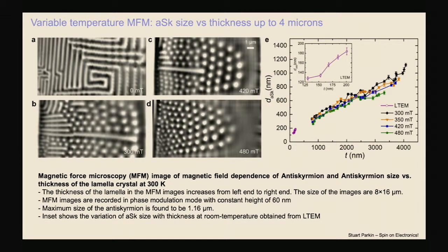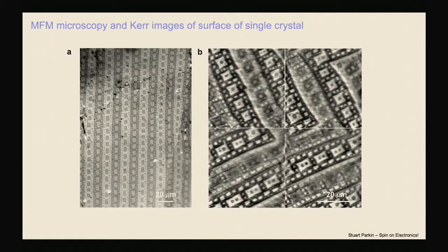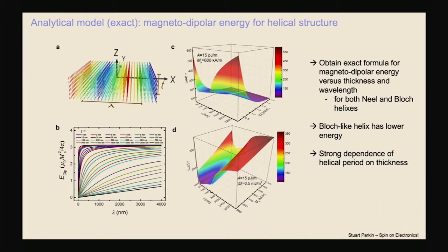This is just to show you the same wedge where we've now stabilized the anti-skyrmion phase by just tuning the magnetic field. And we find that the size of the anti-skyrmion and the period of the helix are in one-to-one accordance, and both of them increase in this linear fashion with thickness. Since my time is up, I'll say we can actually now observe all these structures in single crystals using both Kerr microscopy and magnetic force microscopy.